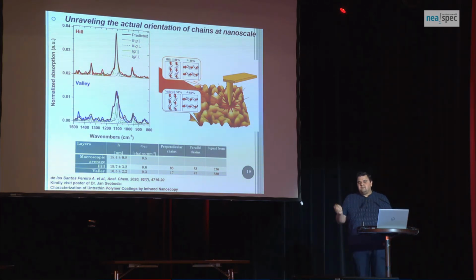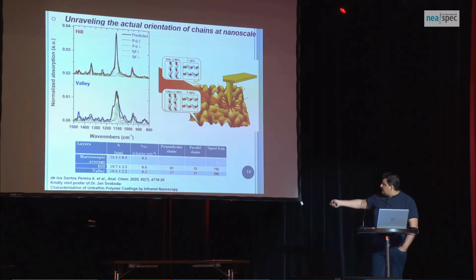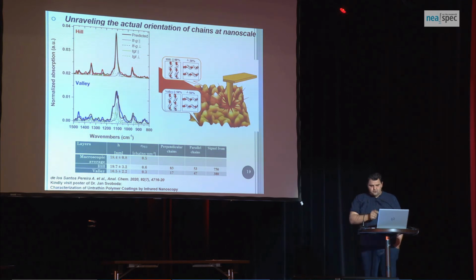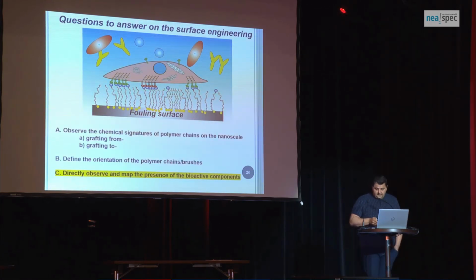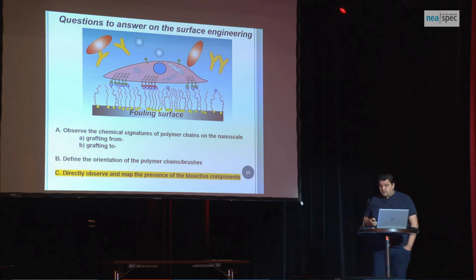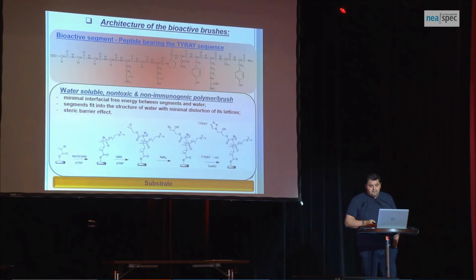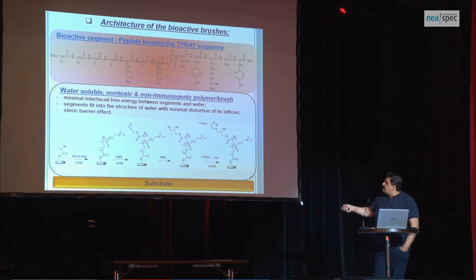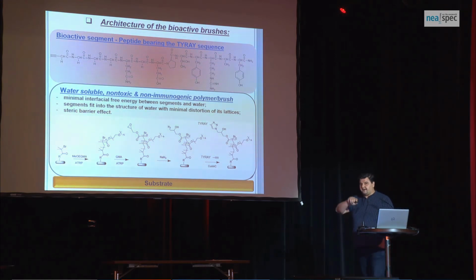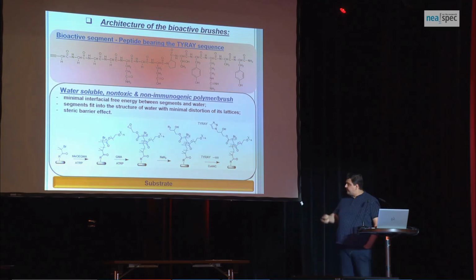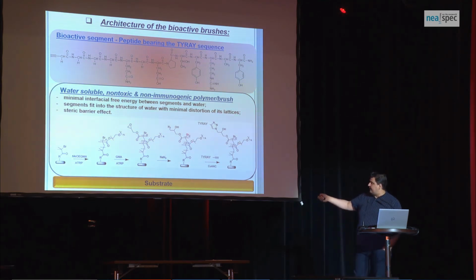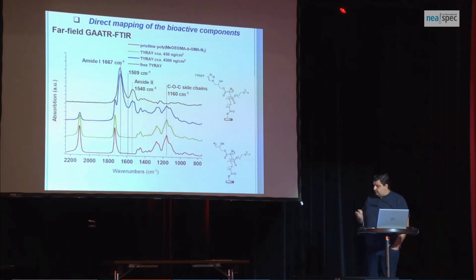And of course, we are not probing individual chains, but we are sampling something like 800 to 400 chains. Let's try to observe if we can directly see the peptide sequences over the surface. This is a peptide which is characteristic for targeting embryonic cells, stem cells. It was bound to the surface by click reaction, so it was bound to something we call a hierarchical brush. Again, we have this monolayer of polymer, with only the second block of the polymer being capable of undergoing this click reaction. And we click the peptide.